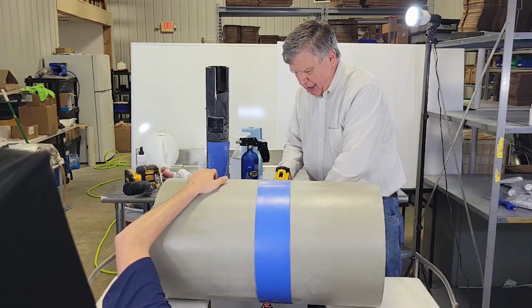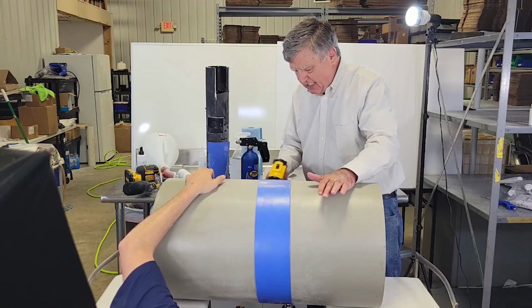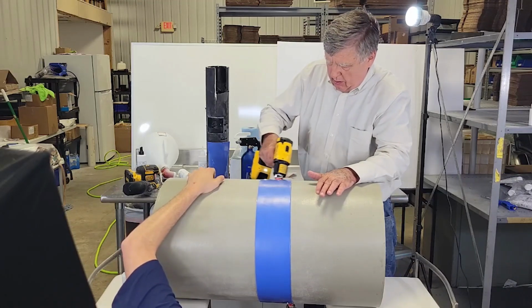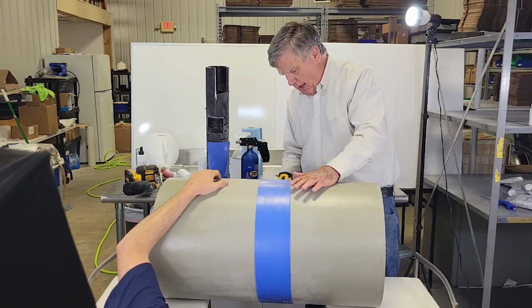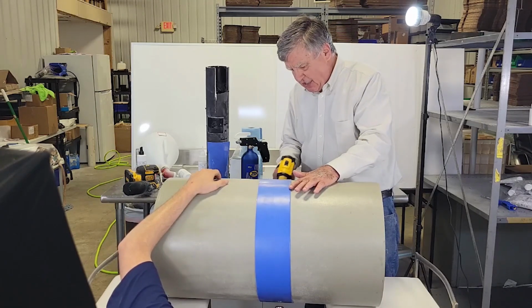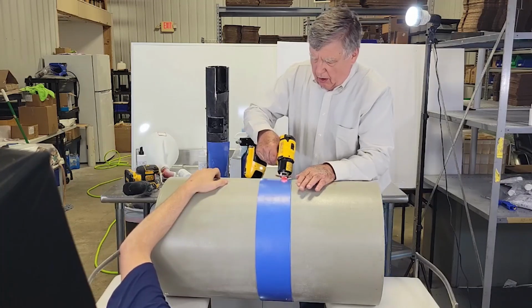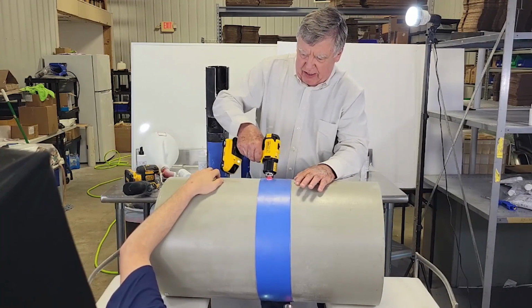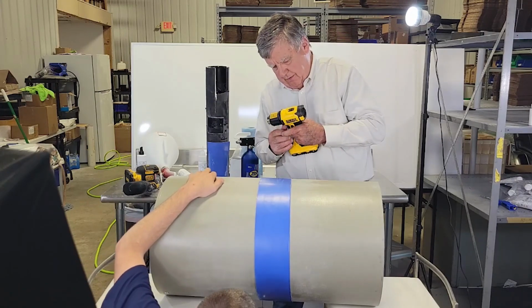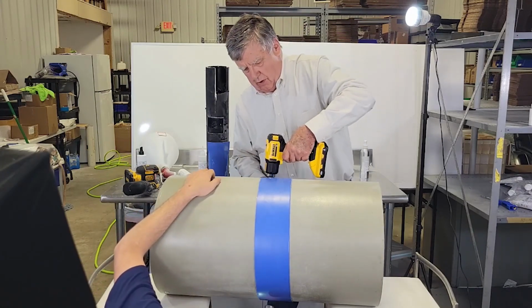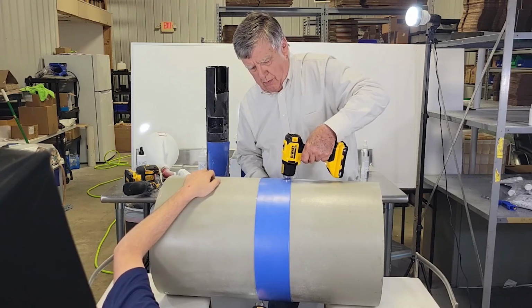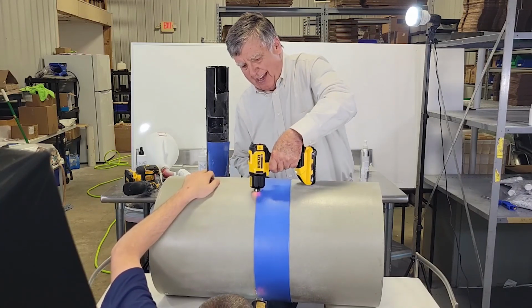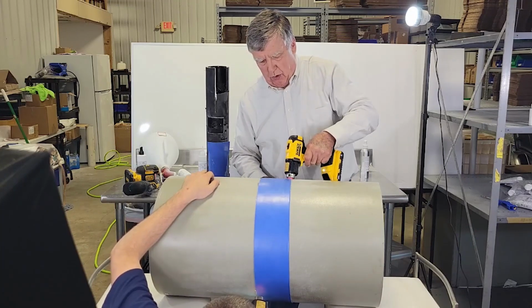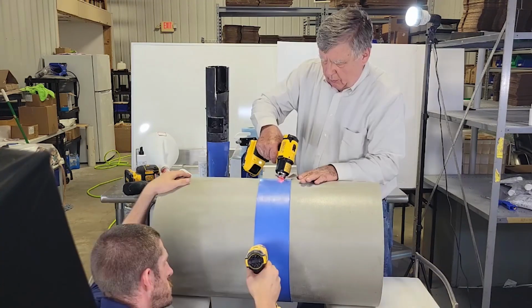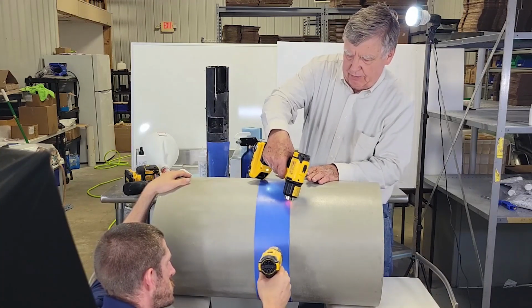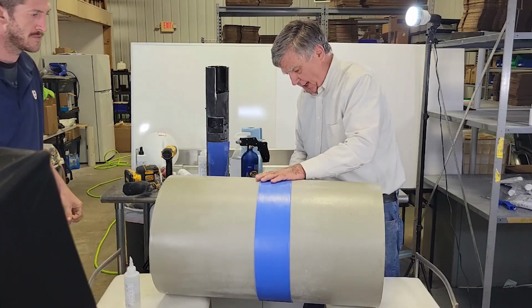The heat has to penetrate the patch and into the HDPE pipe. You will feel the heat take off. It will generate an exothermic reaction. You wouldn't want to do any greater length of area than this, and this was about 5 feet. And then heat, and then do the remaining, whatever that remaining is, in the second application. We're generating that exothermic reaction. It is hot. And that's when you know it's working.